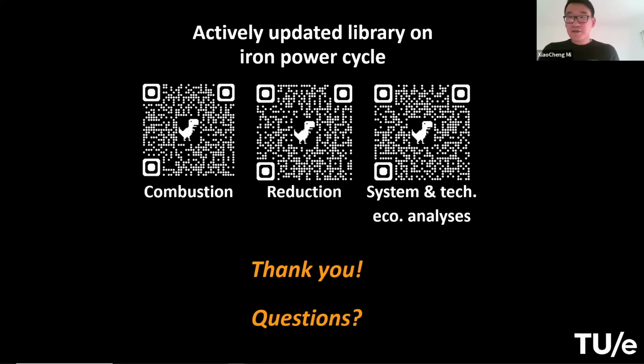Yeah, I think you are talking about the cyclability of the powders. Indeed, we did some research, which I didn't include here. We tried to check whether the particle properties remain the same. What we found is that after the first 2 or 3 cycles, the properties may change quite a lot. This is mainly because the initial particles may have different properties and impurities. But after 2 or 3 cycles, the properties, for example the size of the particle and the oxidation and reduction degree of the successfully ignited particles, remain more or less stable. So we should expect the performance to be stable. But this problem that I mentioned about ignition is more of a technology-limited problem, so we need to improve the technology to make sure you don't have iron particles that fail to be ignited.